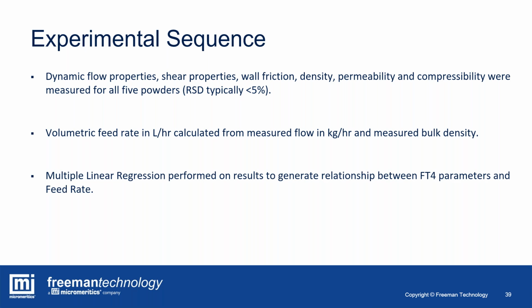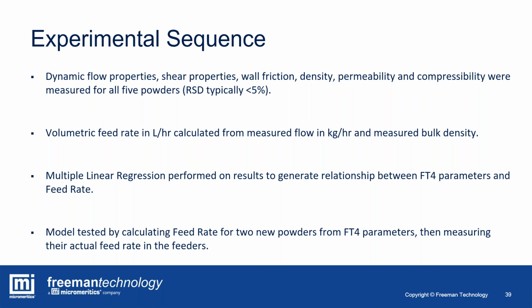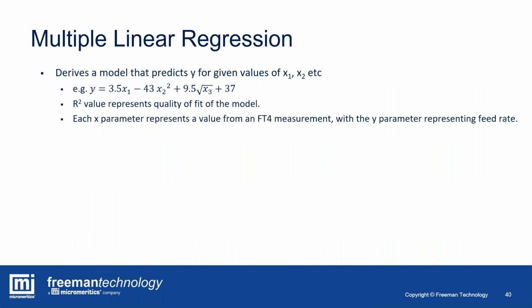We used multiple linear regression on the results to generate a relationship between the FT4 parameters and the feed rate. And then we tested that, of course, by calculating feed rate for 2 new powders from measured FT4 parameters and then measuring their actual feed rates in the hopper. So we wanted to challenge that model. I'm sure you're familiar with multiple linear regression, but very briefly, this derives a model that predicts an output Y for given values of X1, X2, etc. And R squared value represents the quality of the fit of that model. And in this case, each X parameter represents the value of an FT4 measurement, with the Y parameter representing the feed rate.